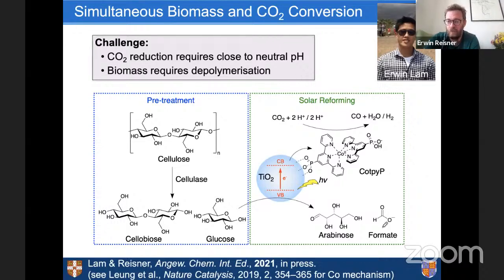And that's the whole system, how it looks. So we photoexcite titania, electrons flow with little driving force, but still sufficient for this molecular co-catalyst to reduce carbon dioxide and water to carbon monoxide and hydrogen. So it's actually syngas. And then we can source the electrons from the glucose and cellobiose following the depolymerization with cellulase, and we form this arabinose and the formate in solution.